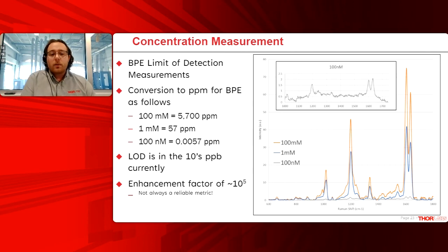Now, this corresponds to a calculated enhancement factor of around 10 to the fifth. However, I do want to mention that enhancement factor is not always a reliable metric. I've actually linked another paper down below that goes over how enhancement factor can change depending on the molecules you're using, depending on the orientation that they fall onto the surface of your substrate, depending on how you estimate the number of molecules that are on your surface. So while many people would like to know enhancement factor, we feel this is not a reliable metric.